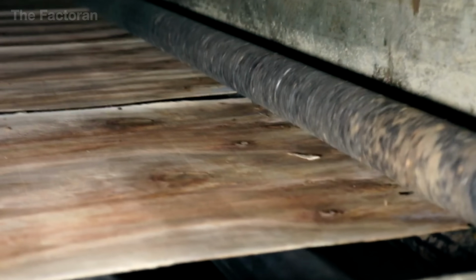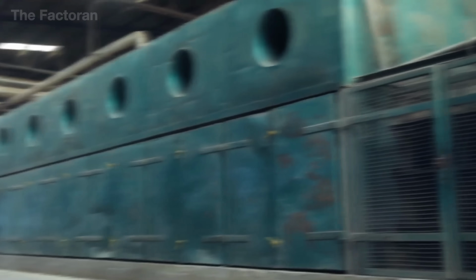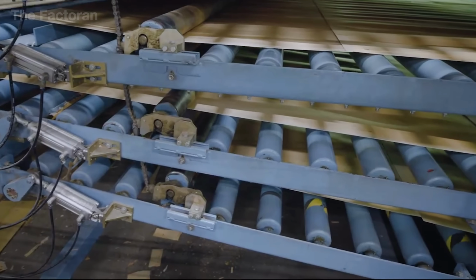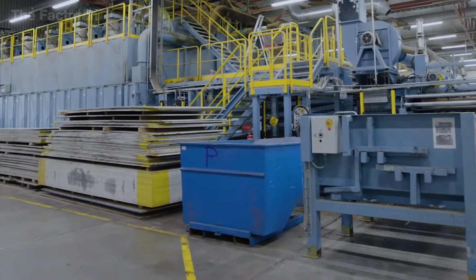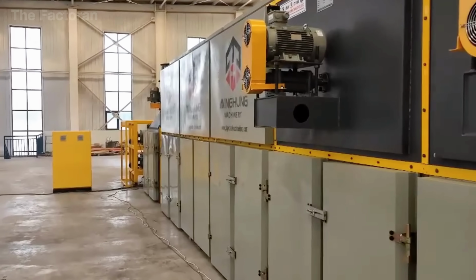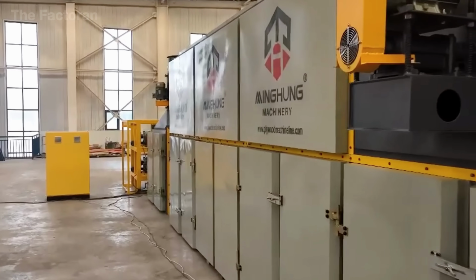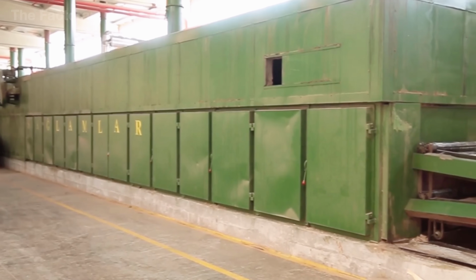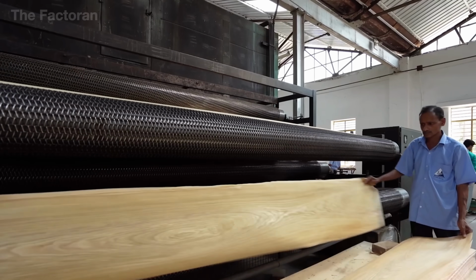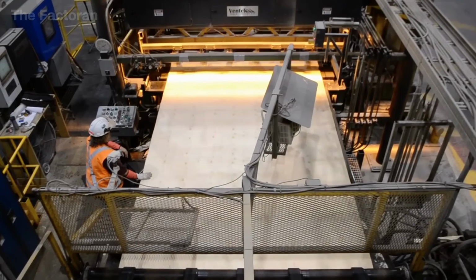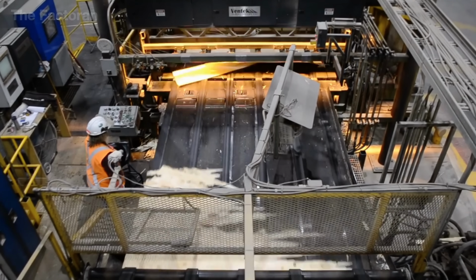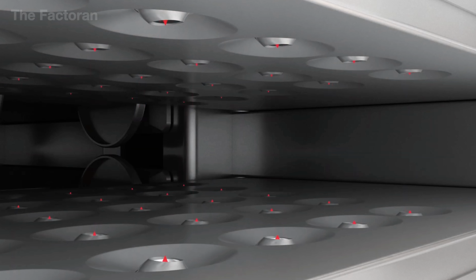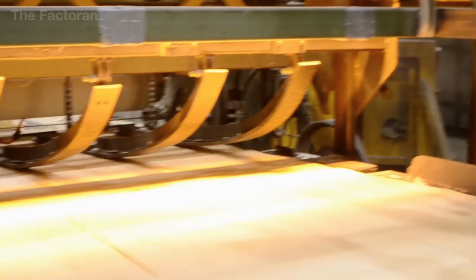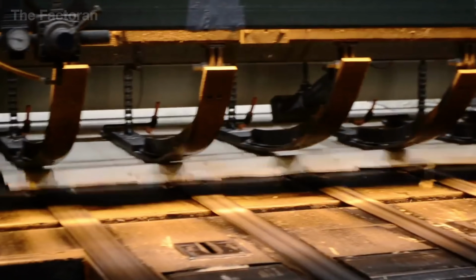Freshly peeled veneer still contains a high level of moisture, often exceeding 30%, leaving the sheets soft and prone to deformation. To achieve stability, they are fed into specialized drying systems, long hot air chambers stretching for tens of meters, where temperatures range from 150 to 180 degrees Celsius. The thin veneers are placed on conveyors and passed through successive heating zones, while powerful fans blow hot air evenly from top to bottom. Within just 5 to 7 minutes, the moisture content drops to only 6 to 8%, the ideal range for preserving both flexibility and mechanical strength.